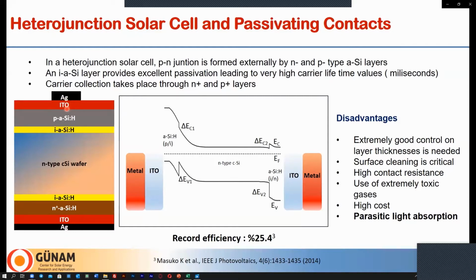And heterojunction solar cells have been very successful in terms of conversion efficiency, with efficiencies above 25% possible. However, in industry, manufacturing has been limited due to some technical difficulties. You need good control on the amorphous silicon layer, especially the intrinsic and P type on the front side. And to deposit this material, you require really toxic material, which necessitates additional investments, which also increase the cost. Apart from fabrication complexities, this solar cell is known to have some parasitic light absorption on the front side because P-type amorphous silicon has a very low band gap.